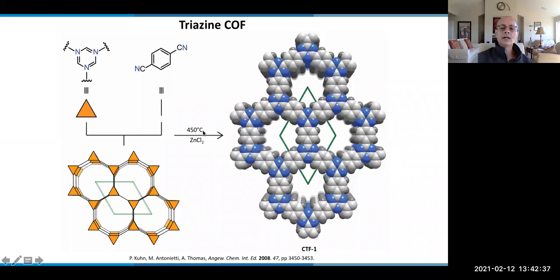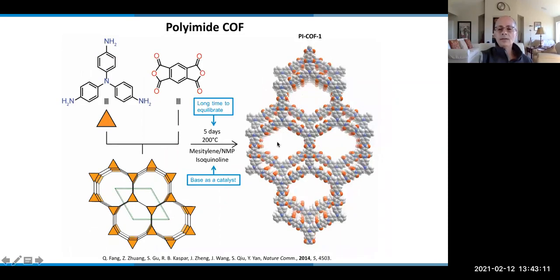Now, I just want to caution that using high temperature means that we're not going to be able to use functionalities, the organic functionalities that don't survive these conditions. So that's one of the things that you watch out for when you're doing COF chemistry, is that you're trying to crystallize the COFs under mild enough conditions that your organic units can be translated from the molecule to the solid and therefore be able to carry out the chemistry you want in the COF. Imide COFs, now we're using isoquinoline as a catalyst to reverse the reaction and help the crystallization process.